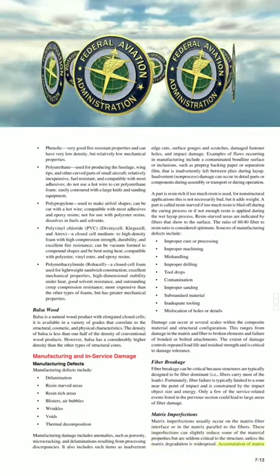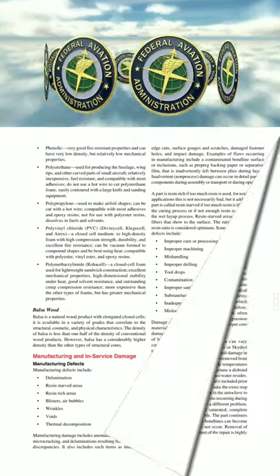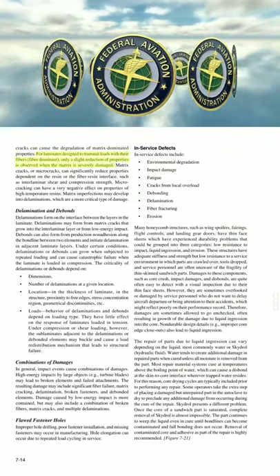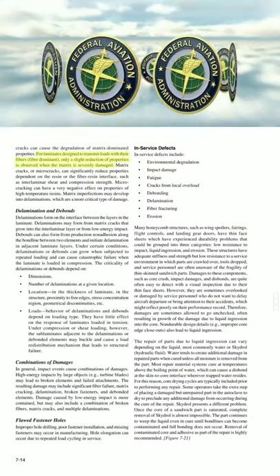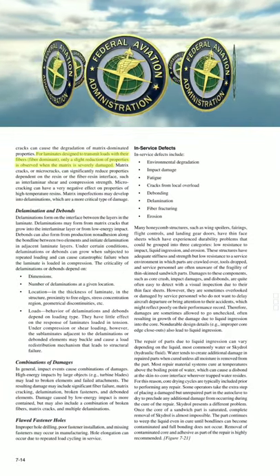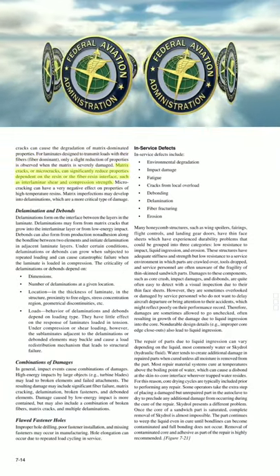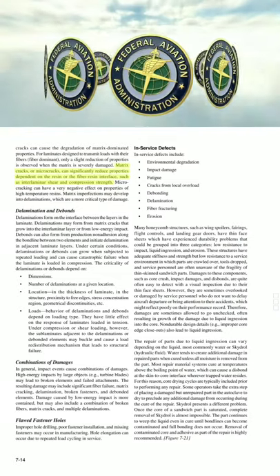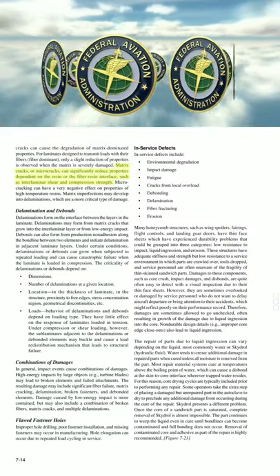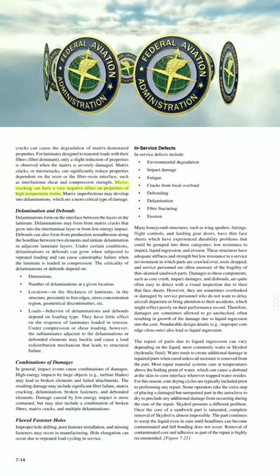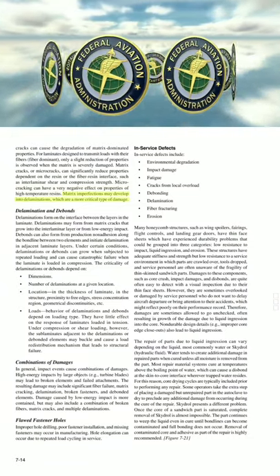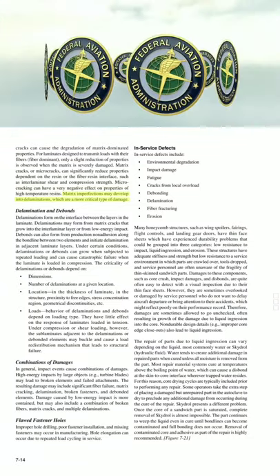Accumulation of matrix cracks can cause degradation of matrix-dominated properties. For laminates designed to transmit loads with their fibers, only a slight reduction of properties is observed when the matrix is severely damaged. Matrix cracks or micro-cracks can significantly reduce properties dependent on the resin or fiber-resin interface, such as interlaminar shear and compression strength. Micro-cracking can have a very negative effect on properties of high-temperature resins. Matrix imperfections may develop into delaminations, which are a more critical type of damage.